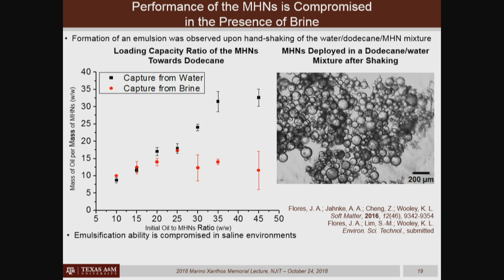And so in the saltwater condition, she was not able to emulsify the sample, and so she reached a peak for the maximum dodecane uptake by these materials, likely through sequestration into the hydrophobic cores of these materials, whereas in an aqueous phase, she could capture the crude oil not only through uptake into the particles, but also through this emulsification effect.